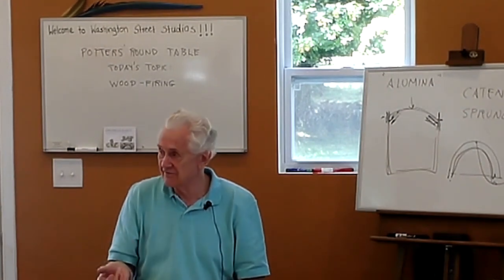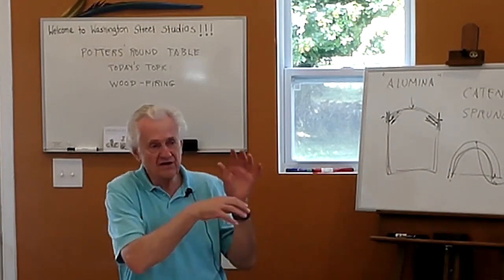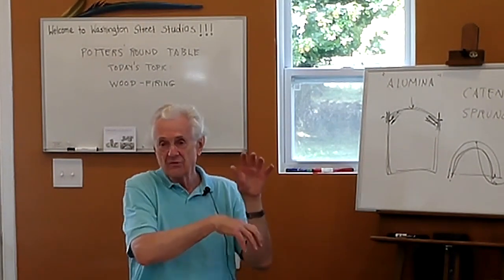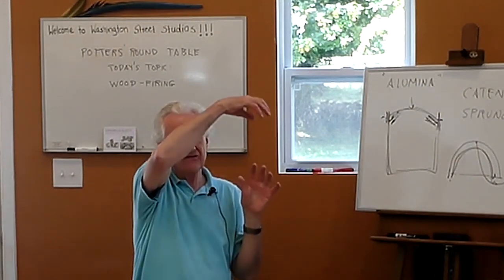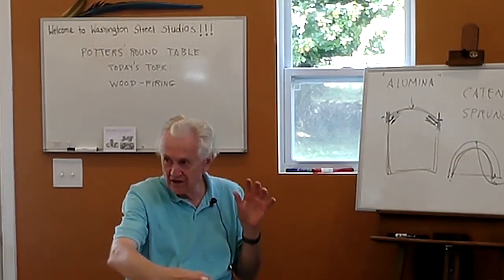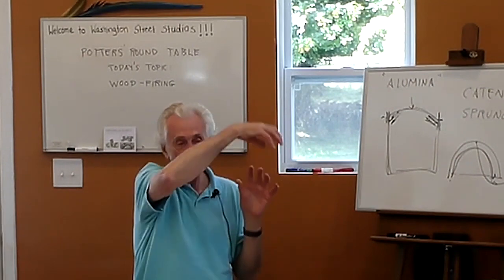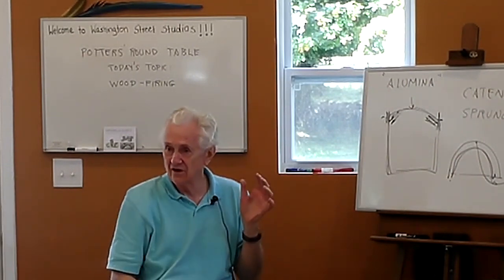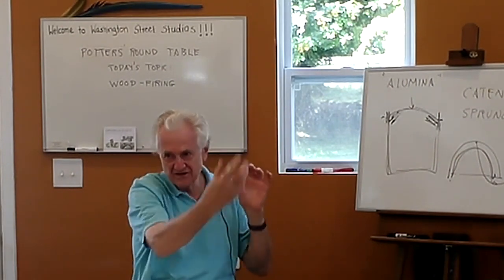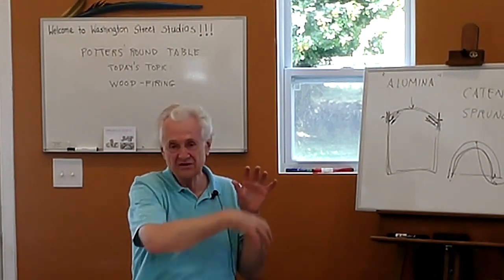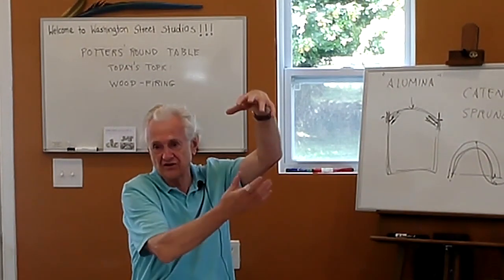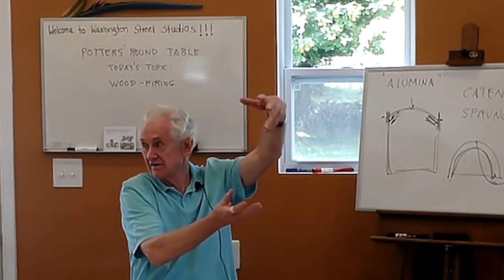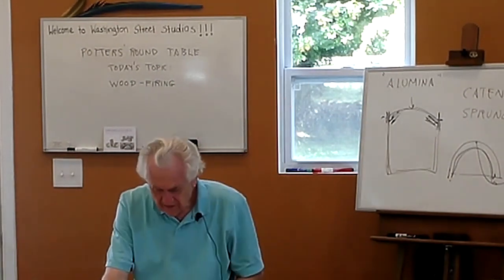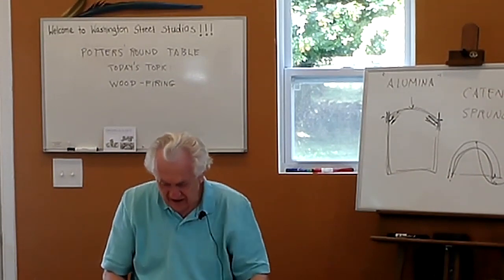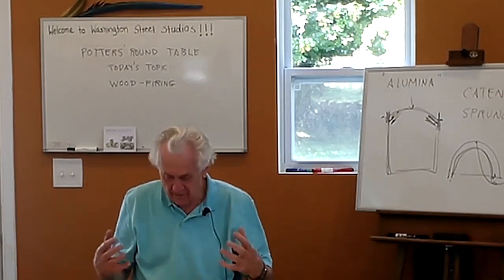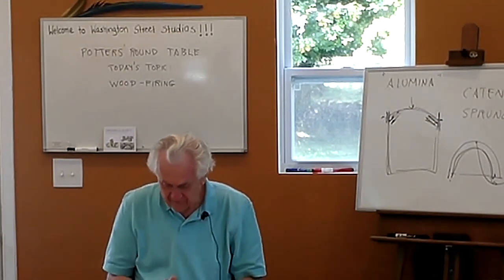If it's a downdraft, then you've got to do more preheating, because hot gases want to rise. If I've got a kiln chamber where I'm making the gas come back down before it can go out, then I've got to create enough draft to pull it back down. So with a downdraft chamber, I definitely need to preheat the chimney to be able to pull it out. Otherwise, the gases just accumulate in the chamber, and the fire won't burn efficiently. And so generally with a wood-fired kiln, you can increase the size of the fire and the amount of wood as the draft improves.